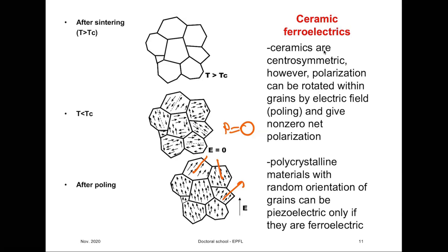We will usually not have any of the grains in a ceramic be single domain. That's because there will be some strain in every grain due to surrounding material, which doesn't have the same orientation. And while we can get rid of most of the 180-degree domains, some 90-degree domains almost always remain in a sample.